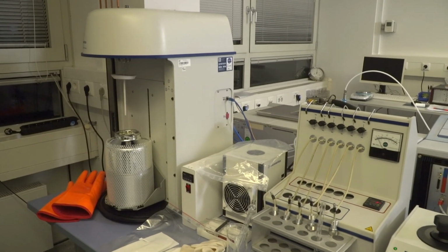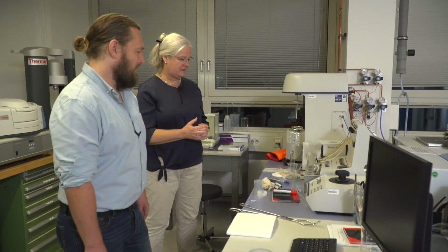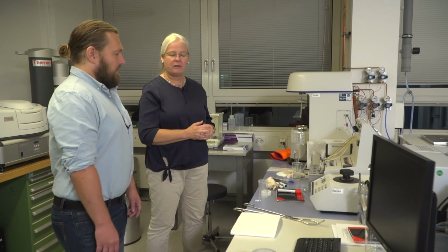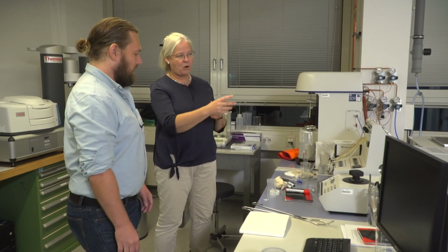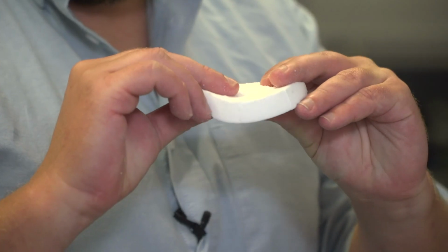And then this is a pycnometer, I believe, right? Yes, this is an AccuPyc, and here we make the measurement of skeletal density. So only the backbone, the solid material. Not the envelope density you get from length, width, and height and the mass, but the density of just the solid part of the aerogel minus all the pores. Very good. We combine these both together to get the porosity.